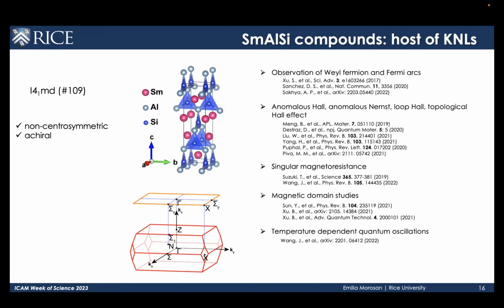So yeah, why do you call it a Kramers-Weyl point? What does it mean? Can you apply a perturbation to open up the gap? It's not the same as a typical Weyl point, and the origin of this isn't the same as the band folding in Weyl semimetals. They come about because of this symmetry enforced pinning at these time reversal invariant momenta, at these high symmetry points. So they're not the same as the Weyl points in Weyl semimetals. Why not call it a Dirac point if it's doubly degenerate instead of just Weyl?